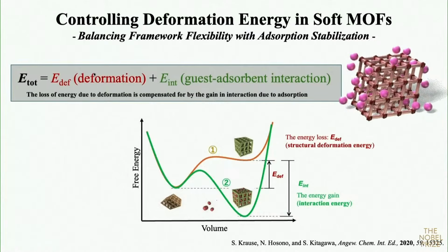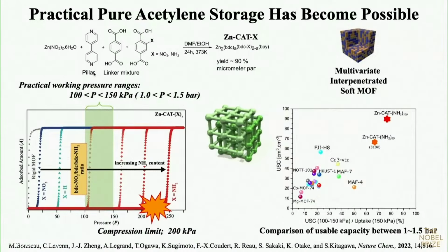So we did. Here, the interpenetrated structure, the unit has zinc, benzene dicarboxylate and pyridine. So we control the repulsion energy. We introduce substituents, just like a solid solution structure. And finally, we obtained this type of beautiful result. This pressure range is larger than 1 bar and lower than 1.5 bar. Very safe storage system we can get.